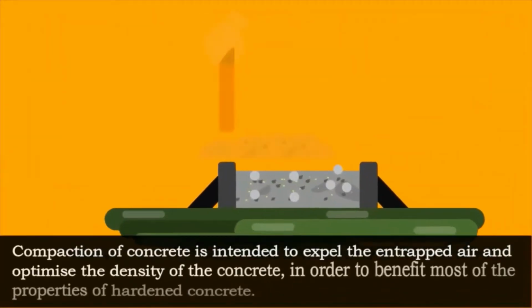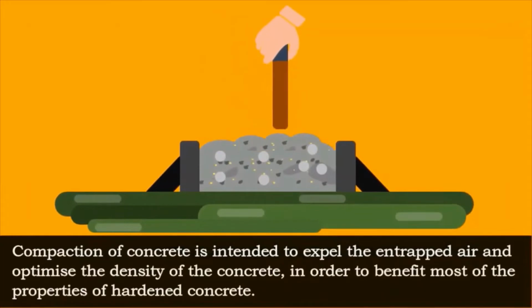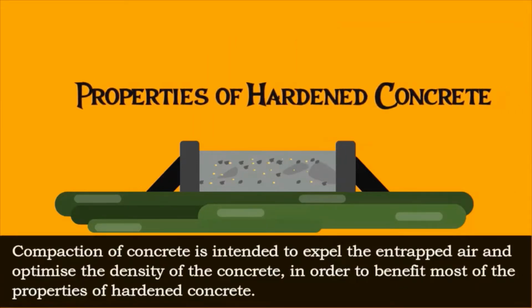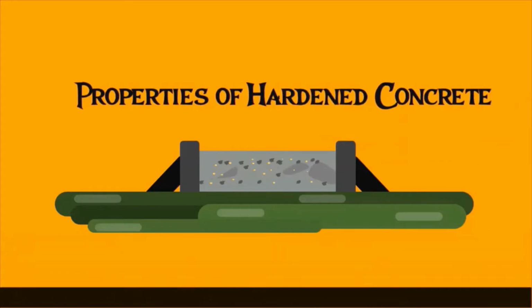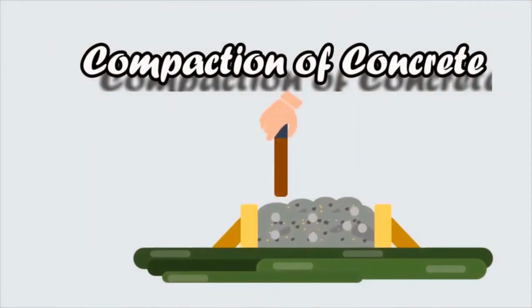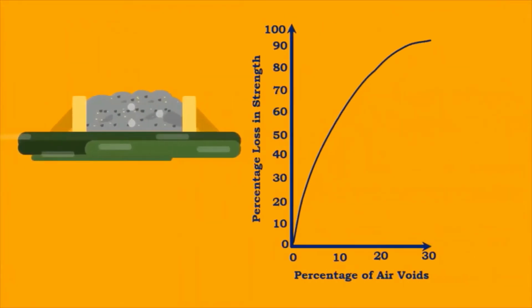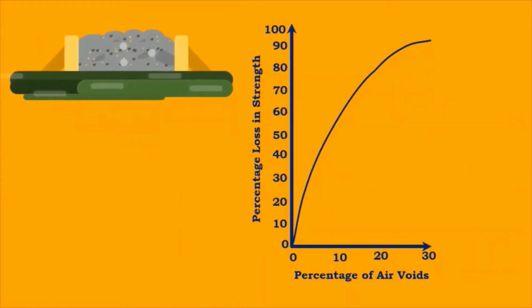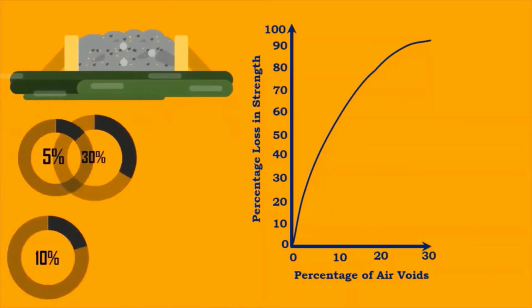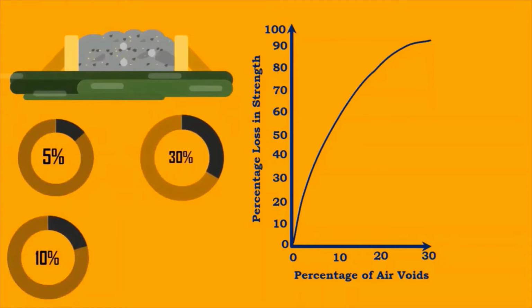Effect of compaction on strength of concrete. We know that the compaction of concrete is intended to expel the entrapped air and optimize the density of the concrete, in order to benefit most of the properties of hardened concrete. We have seen more about this in the video on compaction of concrete. Inadequate compaction leading to air void contents of 5% and 10% results in a loss of strength of 30% and 50%, respectively.